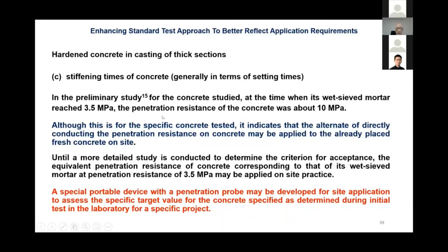So we did it. The same concrete, the wet sieve mortar at 3.5 MPa at that time, that particular mix of concrete showed us about 10 MPa. We did it a couple of times, always around about 10 MPa. So approximately when the wet sieve mortar is 3.5, which we have been taking as a criteria for acceptance, we can now transfer it to 10 MPa in the concrete. That means now it gives us a chance to actually test the concrete on the job site.